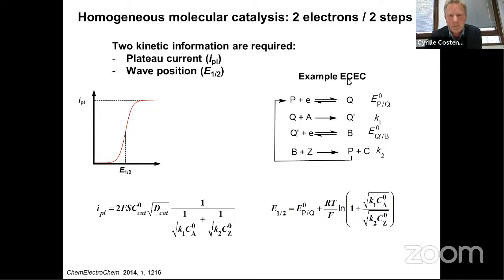If you consider, for example, the ECEC process, which means first an electron transfer, then a reaction with a substrate to make an intermediate that is further reduced, and react with the co-substrate to get the product and regenerate the catalyst, you have 2 chemical steps, okay? If you assume that the second electron transfer is easier than the first one, you will observe just one wave, okay? And so you need 2 kinetic information to characterize the 2 chemical steps.